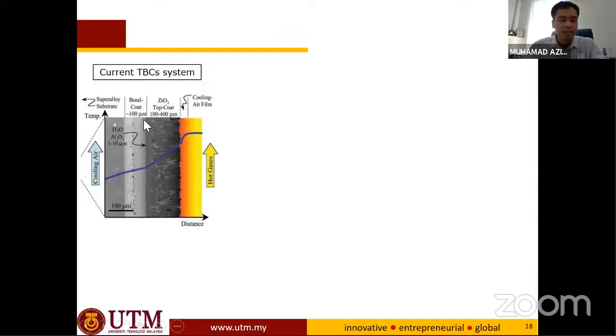If you look at this, in between the bond coat and the zirconia top coat, you can see a line here. This line is what we call the thermally grown oxide. It's not a layer that we coat, but it is formed as a result of high temperature oxidation. The layer formed is alumina. If this layer is thin, it is protective. But if this layer is thick, it develops compressive stress, which leads to spallation of this ceramic coating.